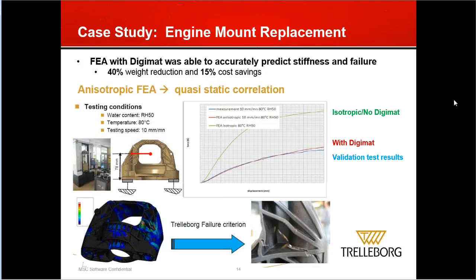You can see the results from the validation step that they did after the design process here on the screen. So using Digimat in the design process, they were able to get a 40% weight reduction, which led to a 15% cost reduction in the manufacturing of the part. In addition, they were able to get very accurate analysis results from their FEA. So in the graph, what you see is a comparison between the validation test results with an isotropic approach, and this is an approach where they're really just pulling the material's properties directly from their material supplier, and then with the Digimat approach. And so what you see there is that the Digimat approach gives you a very accurate prediction of what the force versus deflection curve should look like, so what the stiffness of the part should be.